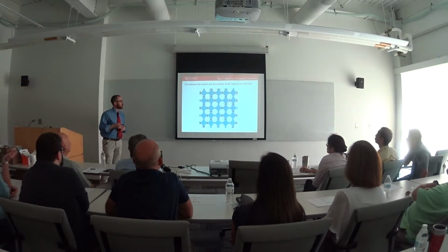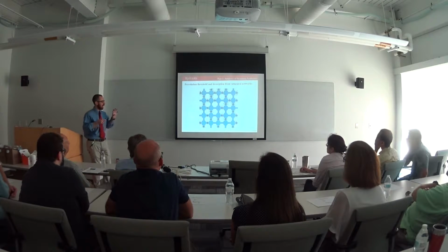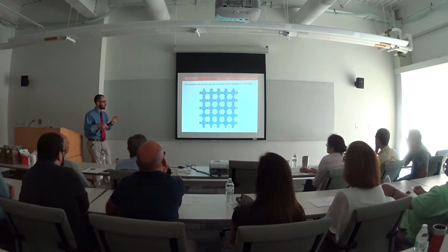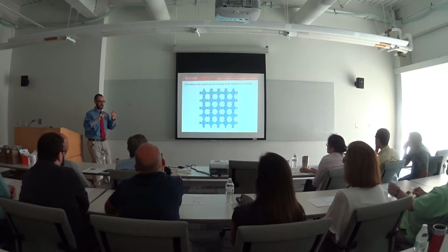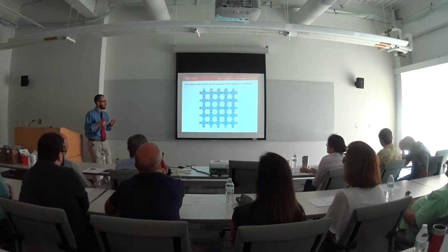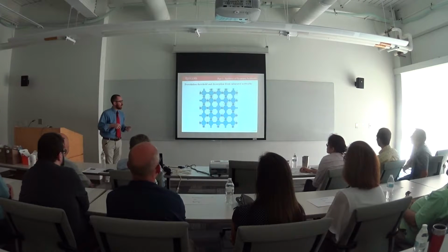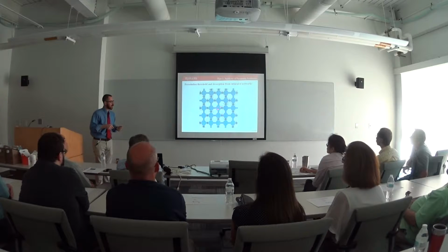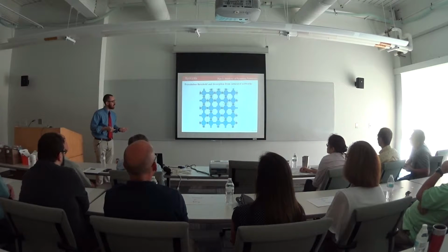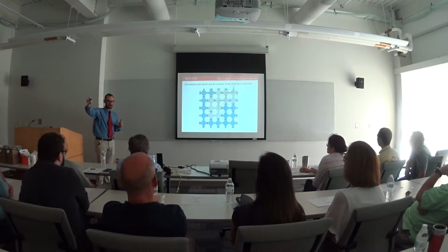So, very briefly, I just wanted to talk about the percolation threshold because it's very central to this piece. If we take this as a model of our pore system, we have pores, which are these spherical bits, and then they're also all connected to necks, which make the lattice connect to each other. The X's denote blocked pores, through which the fluid cannot desorb. What we wish to know is the probability that this pore can desorb, based on the fraction of these necks which are blocked or unblocked. Percolation occurs at the first instance when there is a direct line to the external surface of the material.